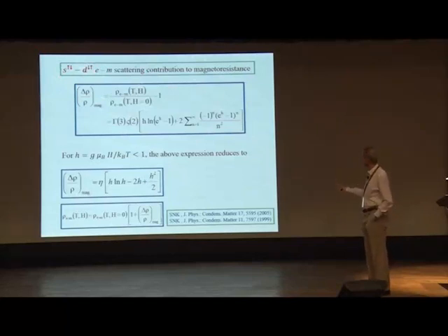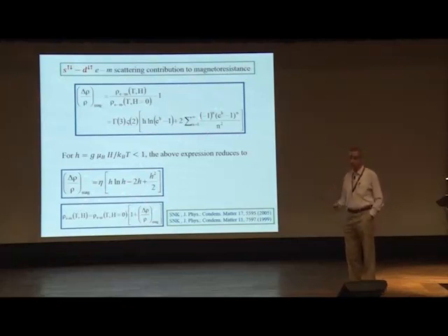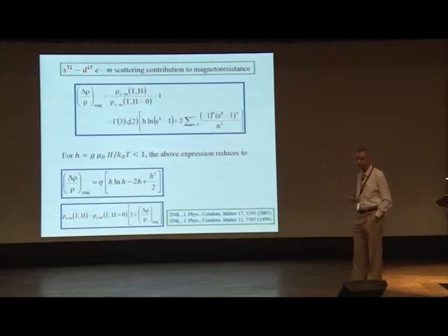Now, this is what theory would give you. You can relate it in various ways. For magnetoresistance, you can measure the isotherms, magnetoresistance versus field at different temperatures, or magnetoresistance versus temperature at different fixed fields. What we did was measure magnetoresistance as a function of temperature at different fields, because we were measuring resistivity in zero field and at different field values, right up to 9 Tesla. So we could get both; you can reconstruct one from the other.